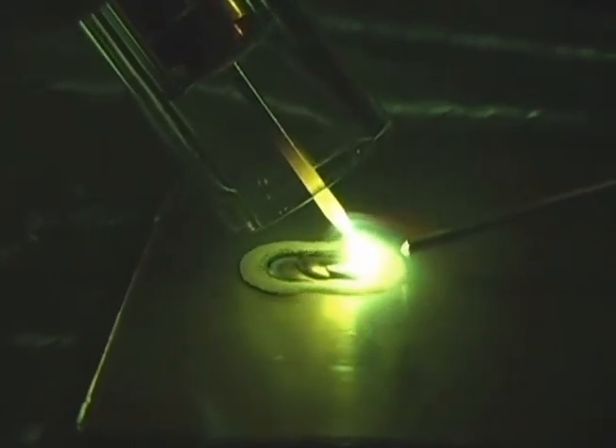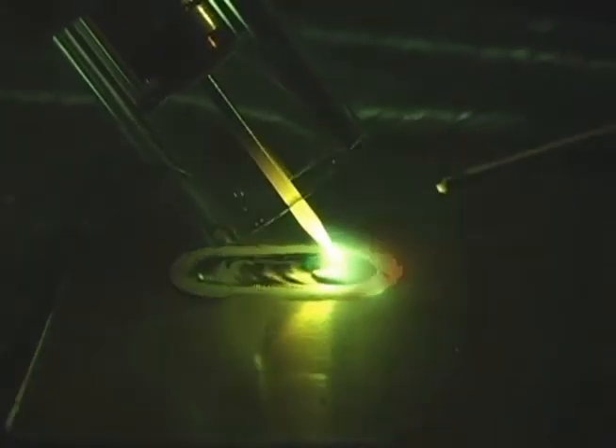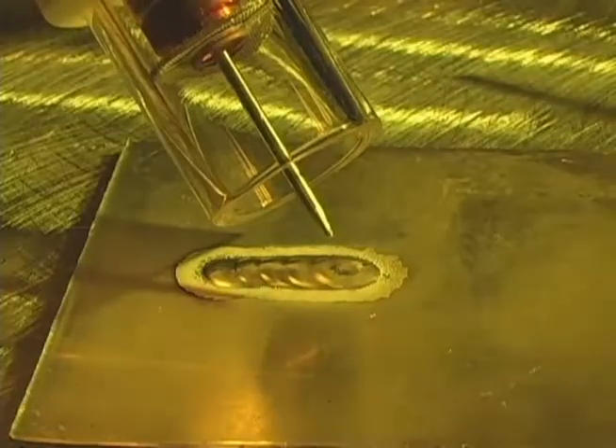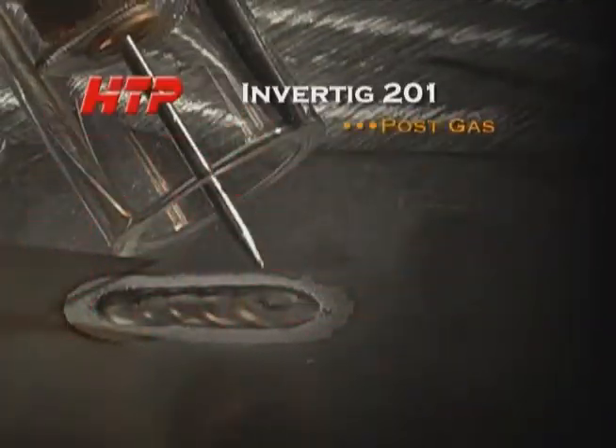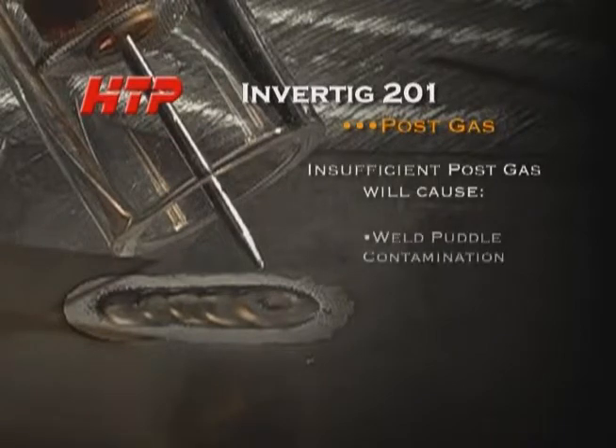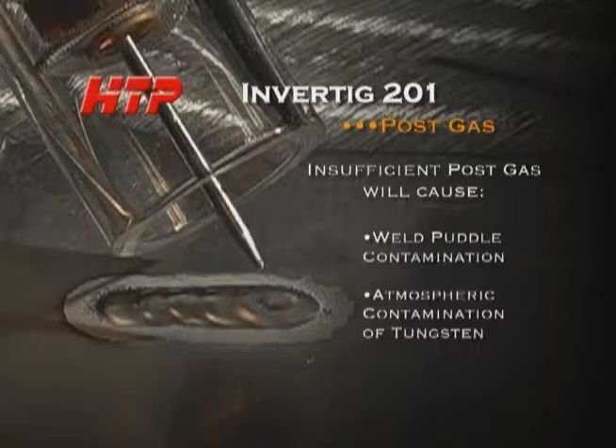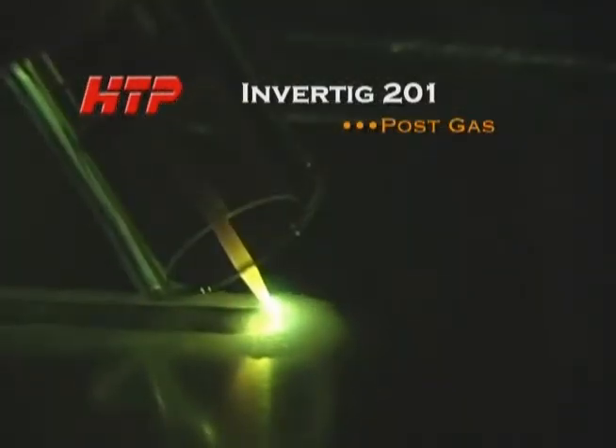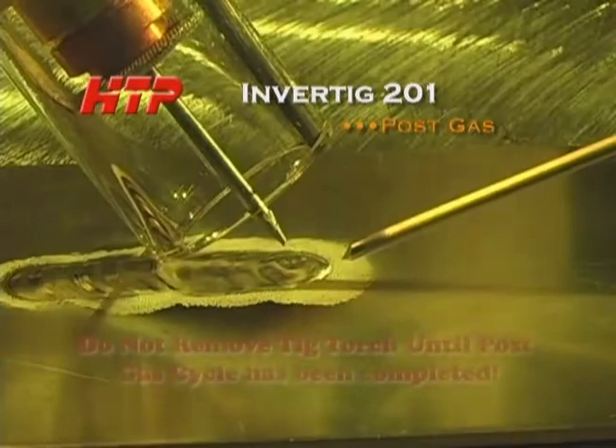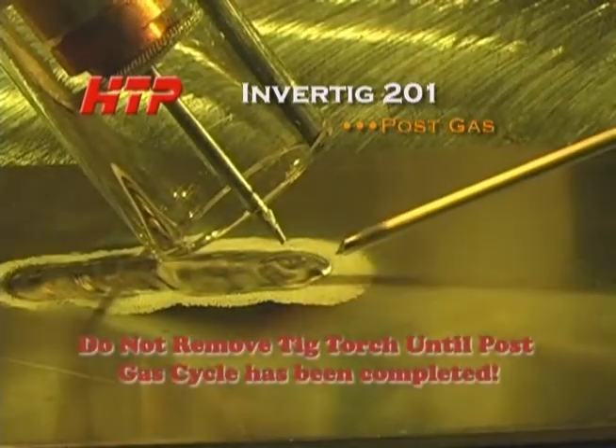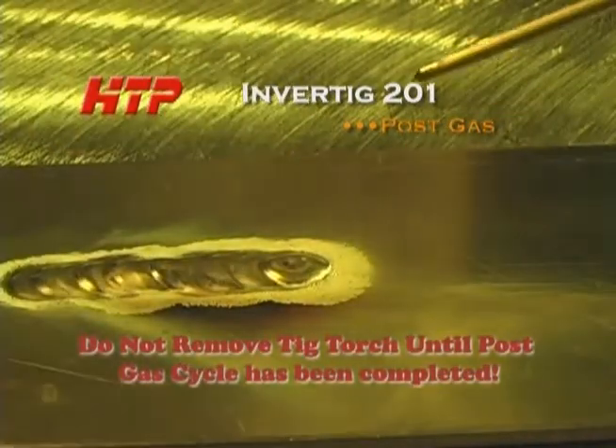Post-gas flow is necessary because after the arc is extinguished, if the gas stopped flowing immediately, there is a possibility the molten weld puddle would come in contact with the atmosphere, causing weld defects. Additionally, it prevents the tungsten from becoming contaminated by the atmosphere. The gas flow should run long enough to allow the orange color of the tungsten to disappear. It is important to remember not to remove the TIG torch from the weld until the post-gas cycle has been completed.